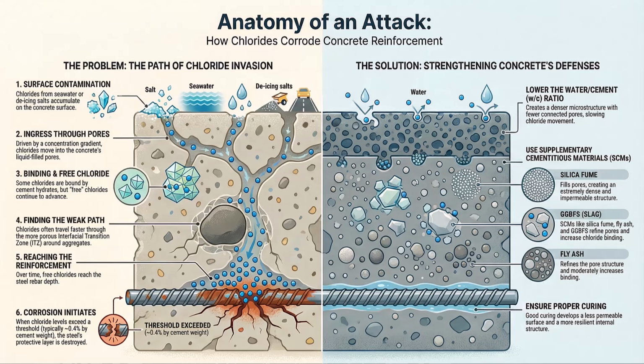Okay, well, we have to start with the severity of the attack. Real project data confirms that engineers have to design for extremely high surface chloride concentrations, often measuring between 1.00 and 3.5% by weight of the concrete right at the surface. That is a relentless chemical assault. Okay, so that's the baseline attack.